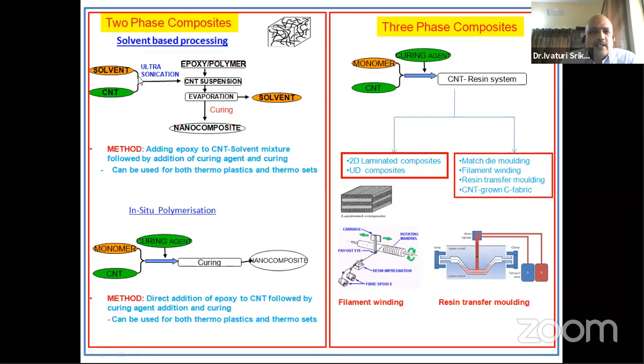So once you have the CNTs purified, functionalized, and dispersed, how do you make the composite? In most laboratory experiments, they take the CNTs, add them into the epoxy resin system, a liquid resin, then pour it into a mold, and realize a CNT dispersed matrix system, as shown here. You can see here, this is only pure CNT in a polymer matrix. The other method is you mix the CNTs, here we have used a solvent. You can see here a solvent is used for ease of dispersion.